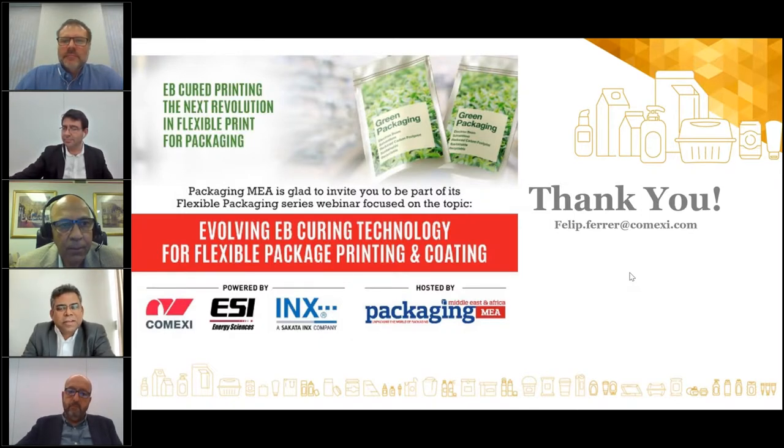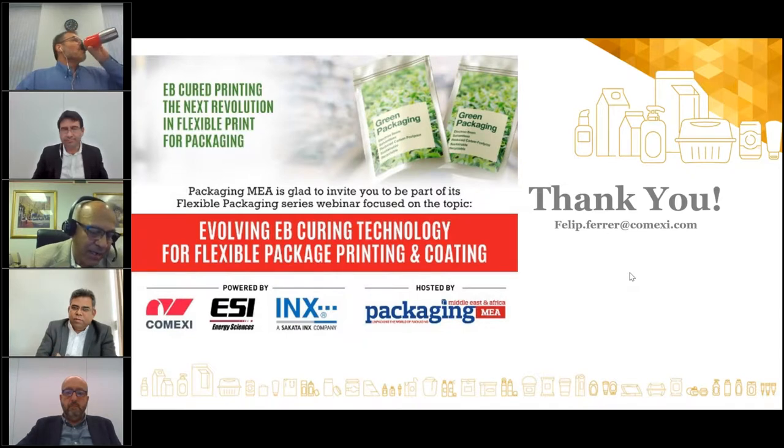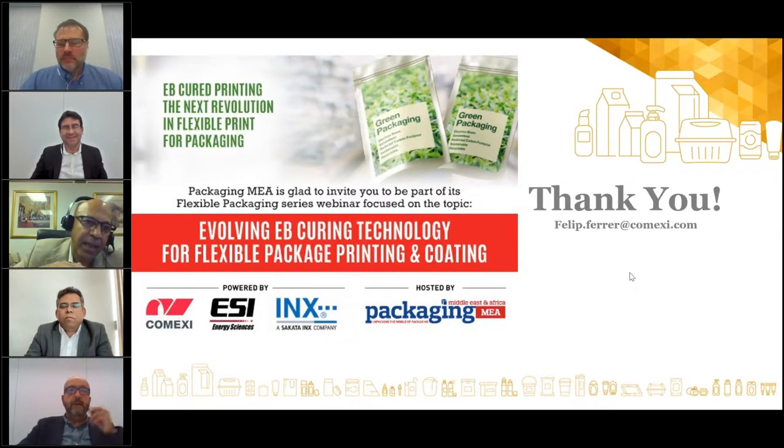Right. Thank you, Mike. I just want to add a little bit more on M&M Mars, just to reiterate, that M&M Mars moved away from a laminate to a monolayer film, getting rid of that 18 micron top layer of OPP and the adhesive, and staying with the cavitated OPP, surface printing it with conventional gravure inks and putting an EB overprint varnish on it. It has been commercial now for over 10 years. There are at least two lines running that for Skittles as well as chocolate M&Ms.